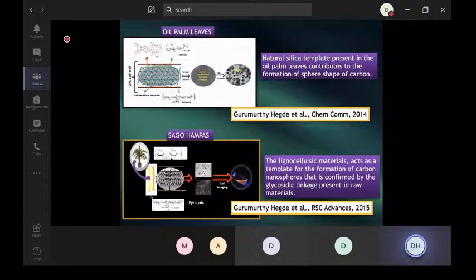That means the porous nature is very important, because sometimes you are not required to have a very highly porous material to make biomedical applications. For biomedical application, you need a very high zeta potential, whereas in energy application, you need a very good surface area. But for biomedical, reasonable surface area with good porous values is sufficient, but they should have very high zeta potential.